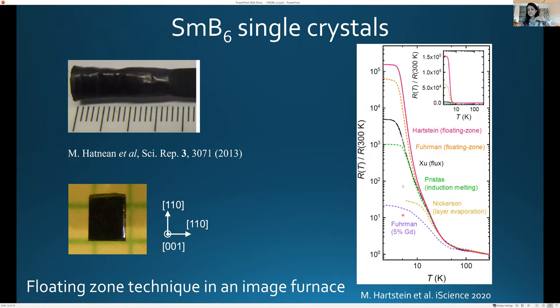And so you can see here that when crystals are deliberately made impure by a small fraction of gadolinium by the group of Tyrel McQueen, I believe, you can see there's a drop of several orders of magnitude of insulating behavior. So it's becoming more metallic. You can see that flux-grown crystals are somewhere in between. They're not too bad, but they do show maybe 10 to the 3.